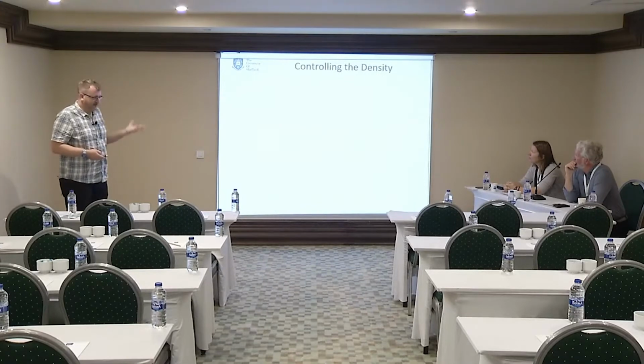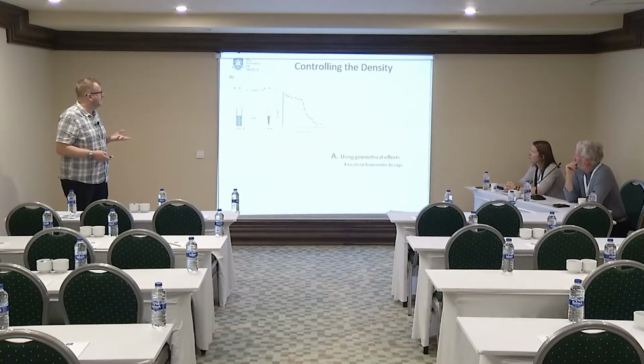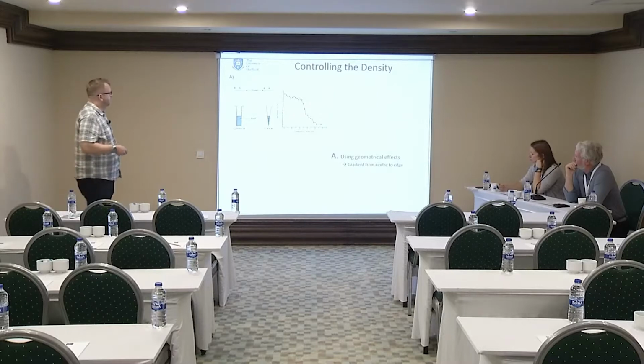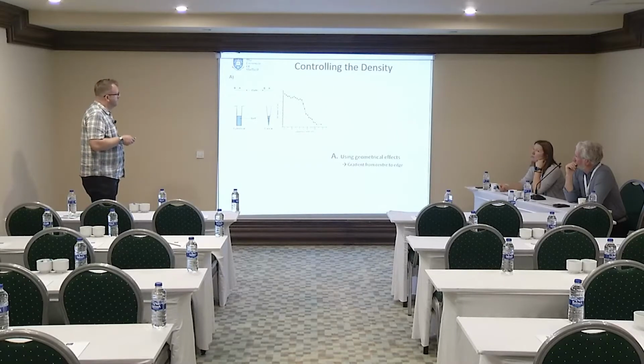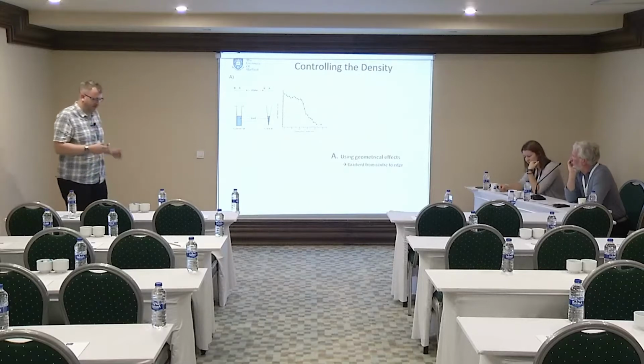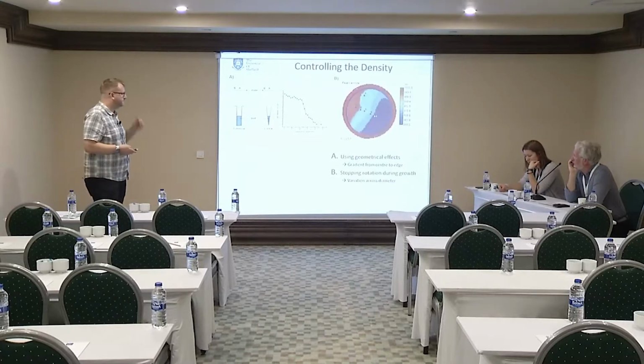So that's just controlling the dot growth. Now we need to control the density. So the simplest thing that we can do is just use the inherent non-uniformity that you might have in certain designs of crucible. So in this case, for a straight-walled crucible, region B doesn't see the entirety of the melt, so the deposition rate is lower here than at the edge, whereas a more conventional, more uniform crucible, region B and region A see the same area. So we see a density gradient from the center to the edge of the wafer. That gives us a ring of the right density.